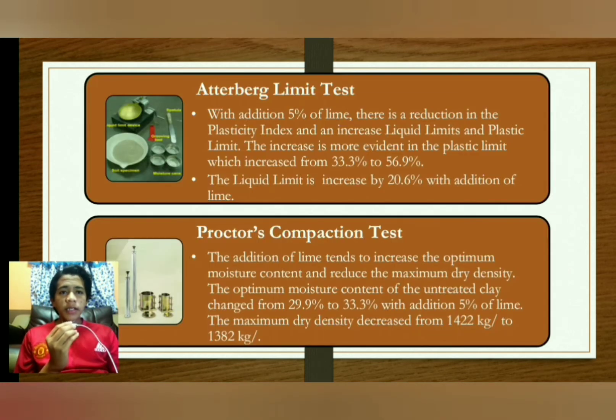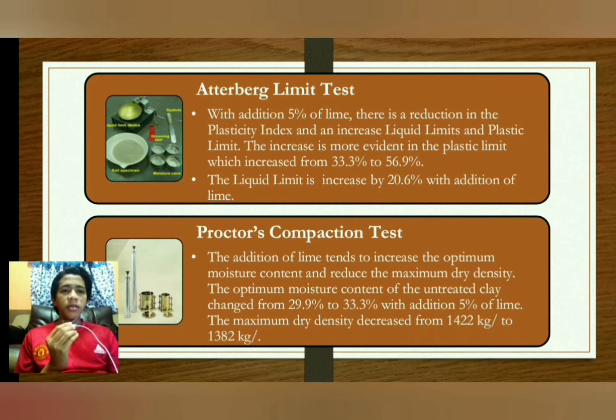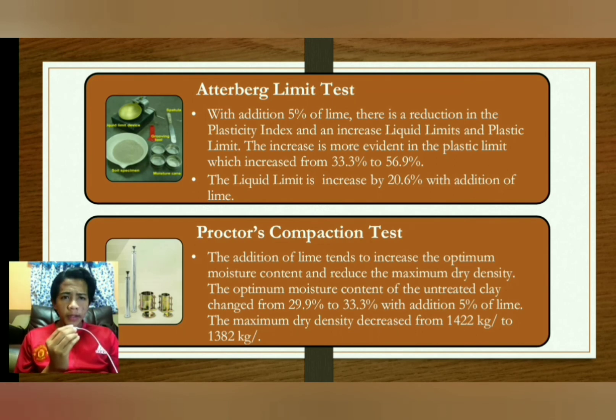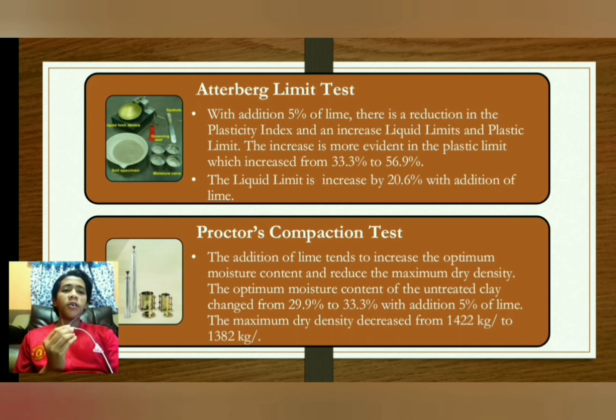The first test is the Atterberg Limit Test with addition of 5% lime. There is a reduction in the plasticity index and an increase in liquid limit and plastic limit. The increase is more evident in the plastic limit, which increased from 33.3% to 56.9%. The liquid limit increased by 20.6% with the addition of lime.